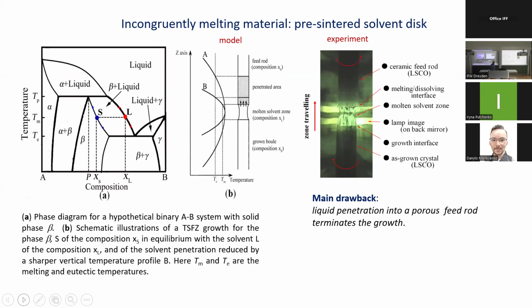So again, using the floating zone technique, we could grow either congruently melting or incongruently melting compounds. The latter task is much more complicated due to the so-called penetration effect caused by feed rod porosity. If our material melts incongruently, we could still apply this technique. We would like to grow this solid composition marked by capital S. We need a molten zone of this composition marked by capital L. And if we know the corresponding phase diagram, it's quite an easy task. We simply prepare a solvent rod, cut off a short disc, attach it to the feed rod and melt it.